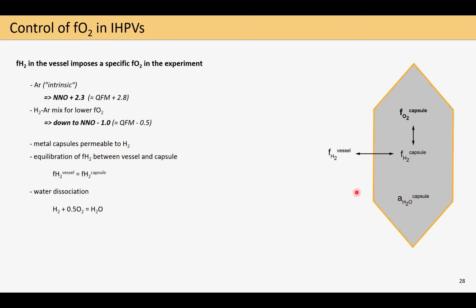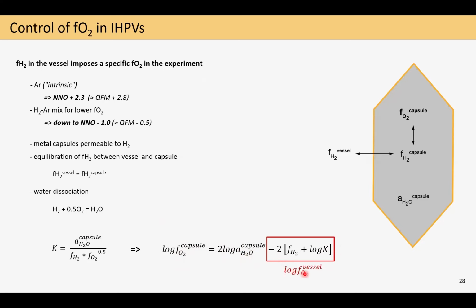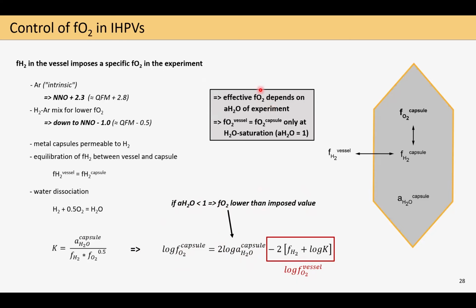will react with the water present there via the water dissociation reaction, and we can then try to calculate the fO2 via the equilibrium constant of this reaction, resulting in the fO2 in our experiments corresponding to 2 times the logarithm of the water activity inside of the capsule minus this factor, which, for simplicity, I will now just call the intrinsic fO2, or fO2 imposed by the vessel. And this equation here means that in case the water activity in our experiment is below 1, the fO2 we will get will be lower than the imposed value. As a consequence, the buffered fO2 conditions in our experiments will always depend on the water activity of each individual run, meaning that the oxygen fugacity we impose with the vessel will only correspond to the fO2 inside of the capsule at water saturation.